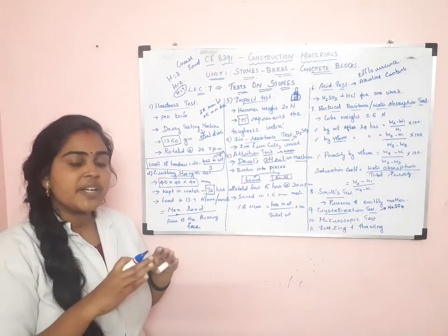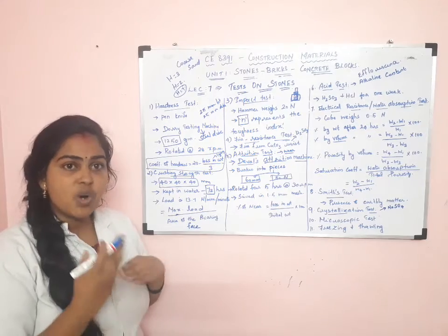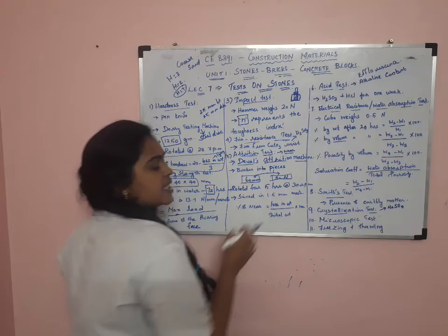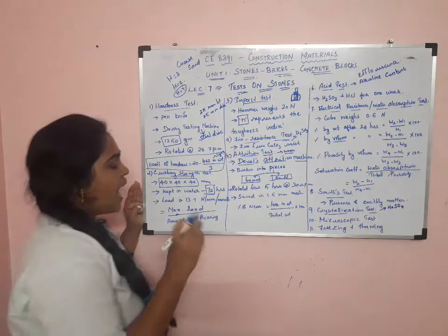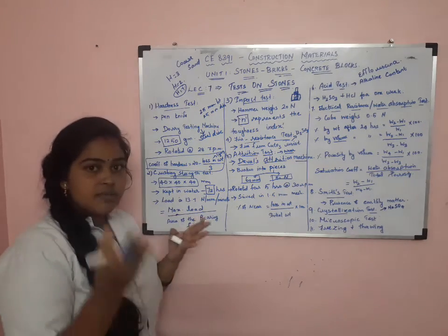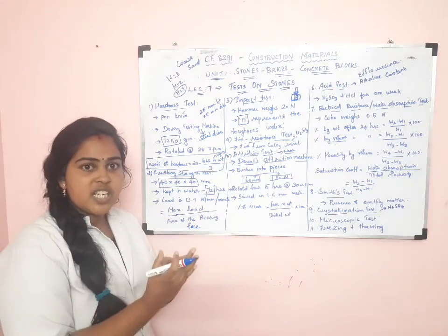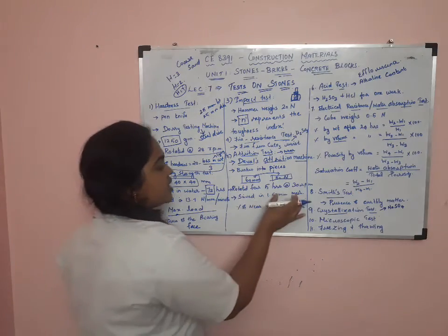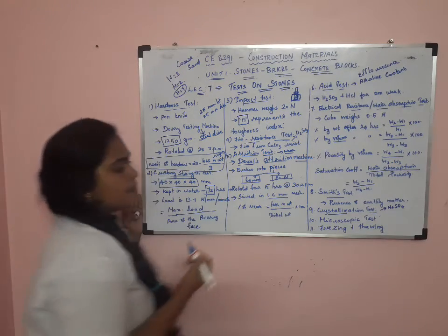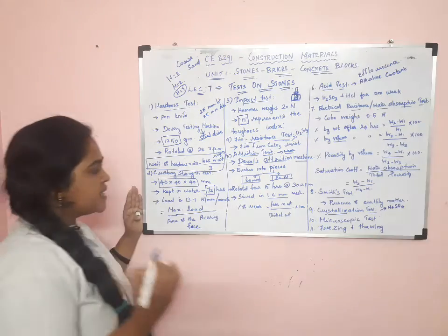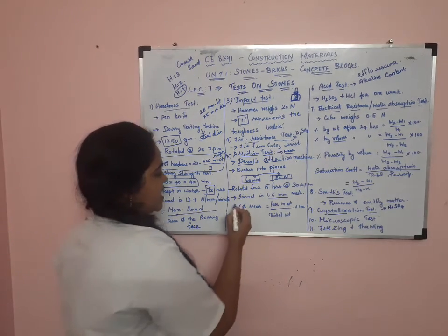The cylinders are rotated about a horizontal axis for 5 hours at 30 revolutions per minute. The leftover crust material is taken out from the cylinder and sieved in a sieve of size 1.6 mm, and the retained weight is taken.